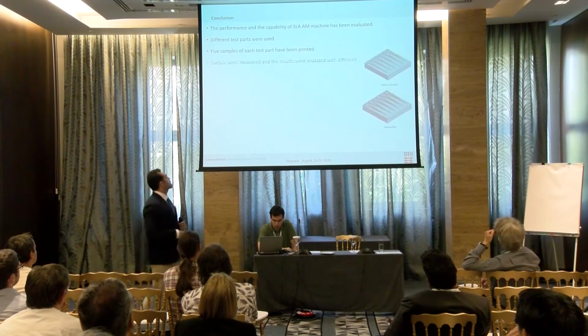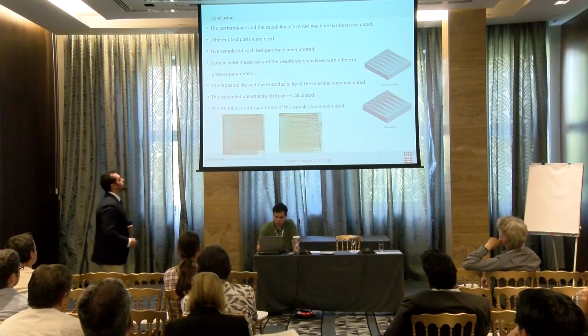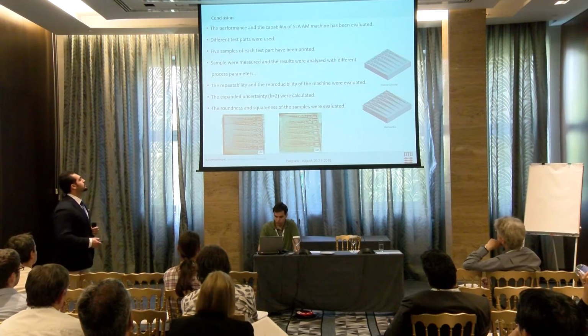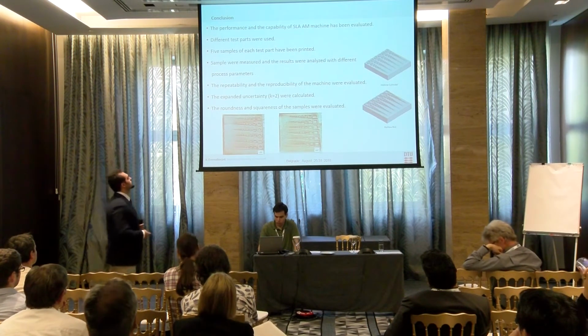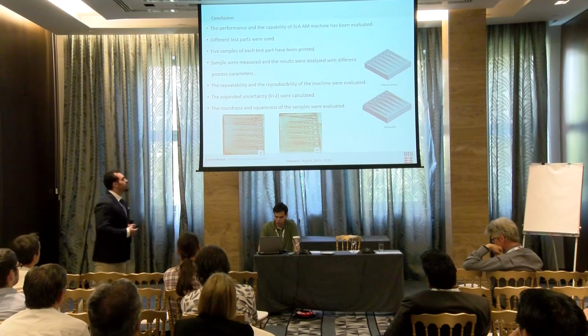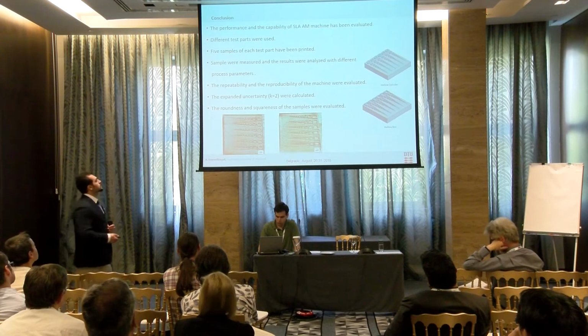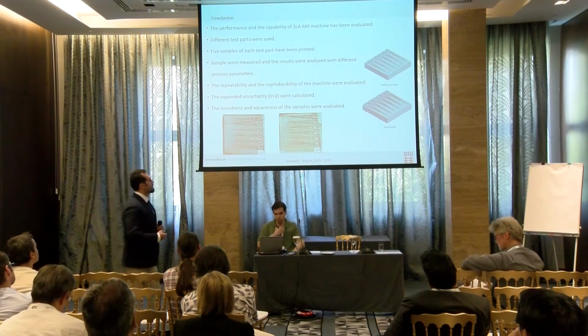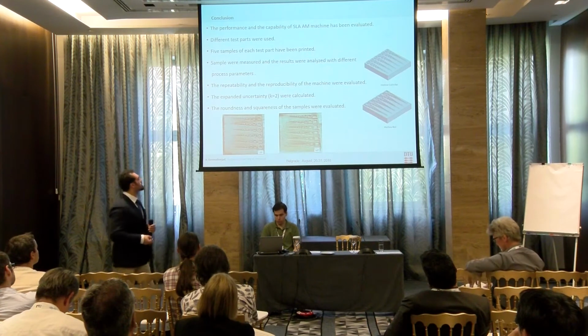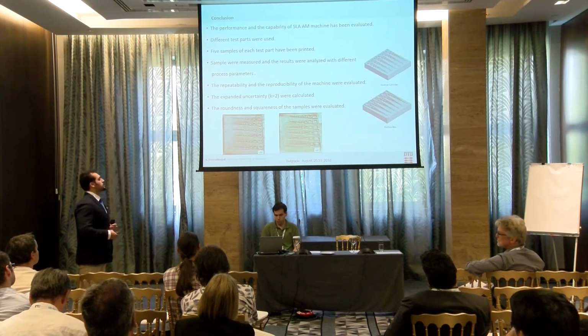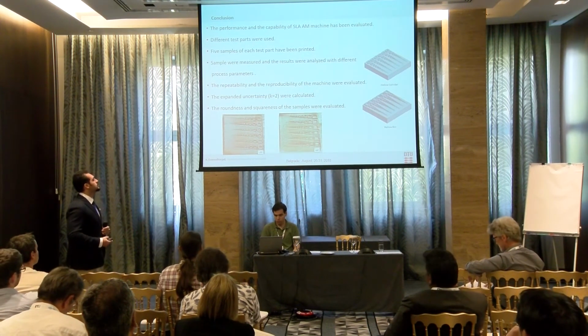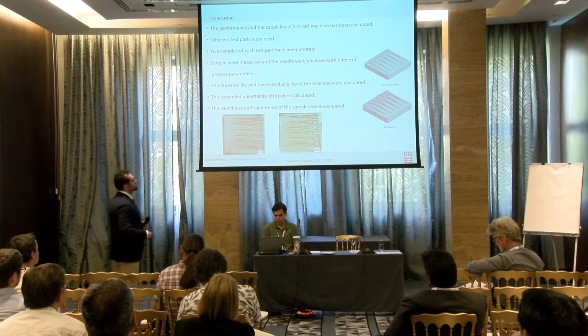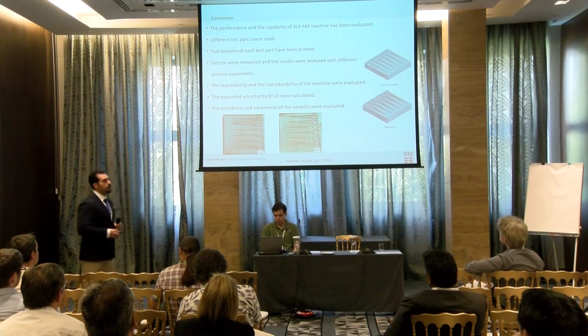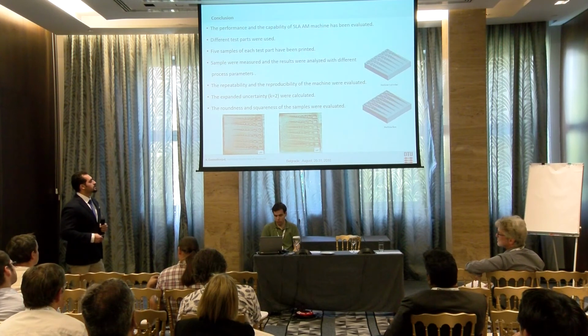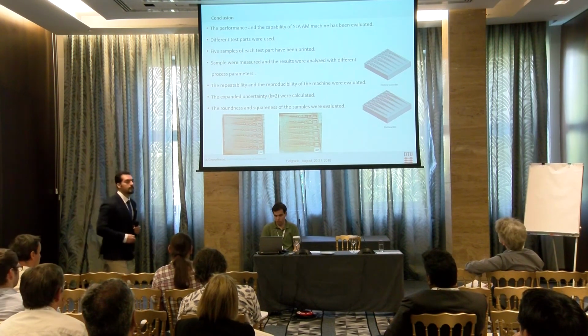Then to conclude, the performance and capability of the SLA machine has been evaluated, and different test parts were used. Five different sample parts have been printed, and the samples were measured and the results were analyzed with different process parameters. The repeatability and reproducibility of the machine were evaluated, and the expanded uncertainty with coverage factor 2 was calculated, and the roundness and squareness of the samples were evaluated.